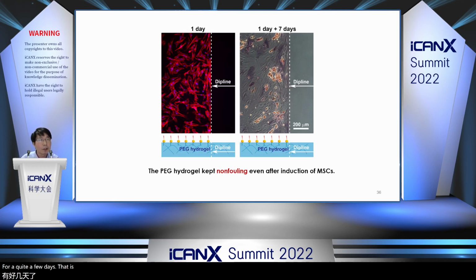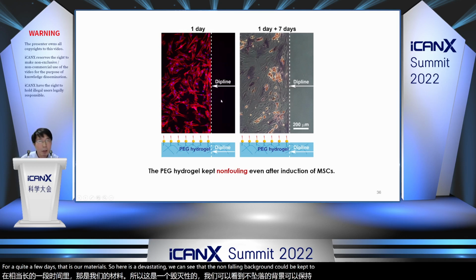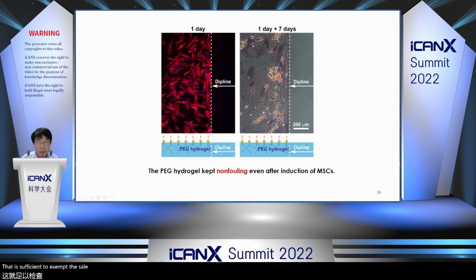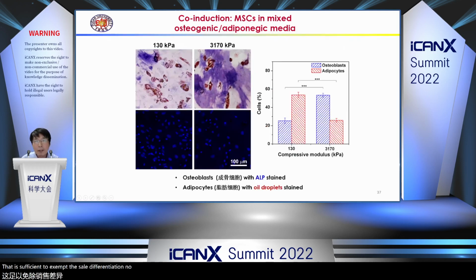That is our material. So here is a demonstration. We can see that the non-fouling background could be kept for at least one week. That is sufficient to examine cell differentiation. Now, here is the differentiation in the mixed medium of osteogenic and adipogenic medium. And we did see the blue color indicates osteogenic differentiation. The red color indicates adipogenic differentiation.